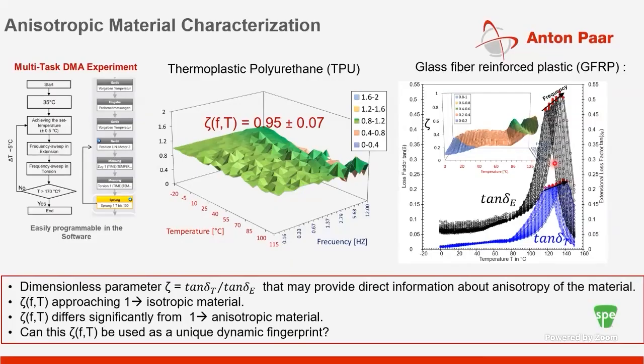If you take a look at this, first of all, look at the loss factors both in torsion and extension, and they are completely different. They don't cater to what an isotropic material looks like, where you see a maximum, which is definitely interpreted as the glass transition.